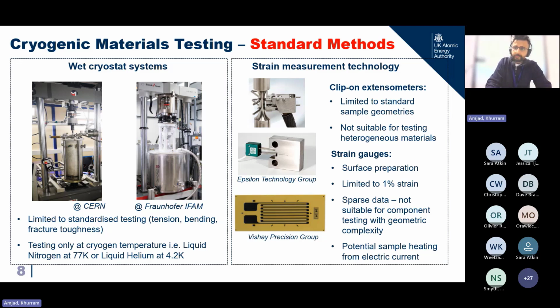And in terms of strain measurement technology, traditionally there is a reliance on clip-on extensometers, which essentially give you a uniform elongation over the gauge section. There are clip-on extensometers for fracture toughness measurements as well, which you would use in your compliance measurements. And then for strain measurements at a given point, I think the industry standard is still the strain gauges. They've been rated to cryogenic temperatures as well.